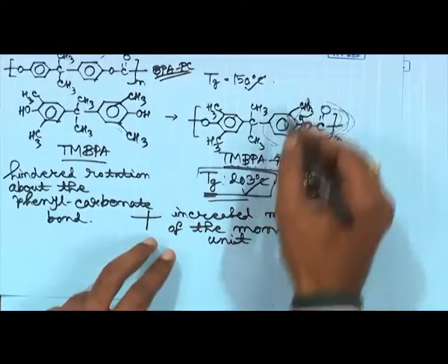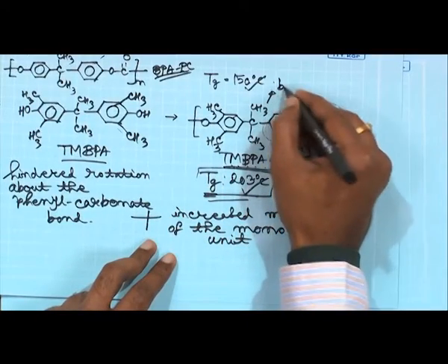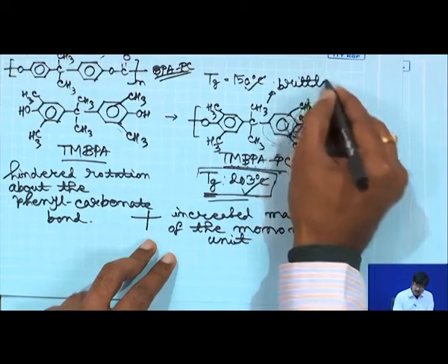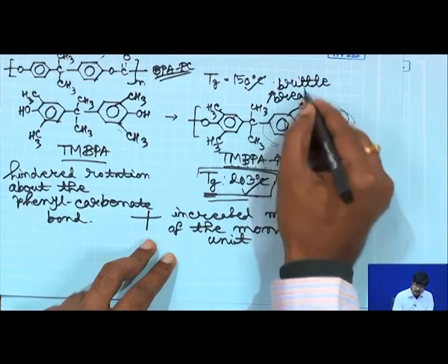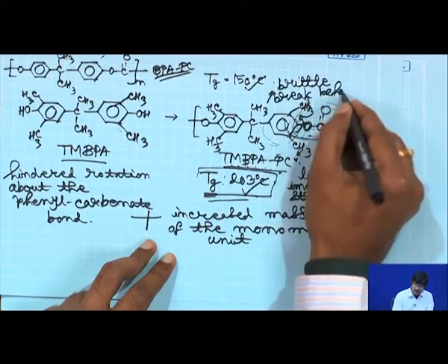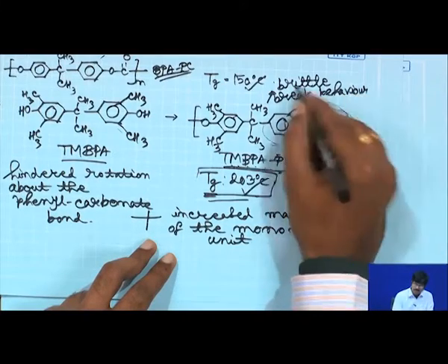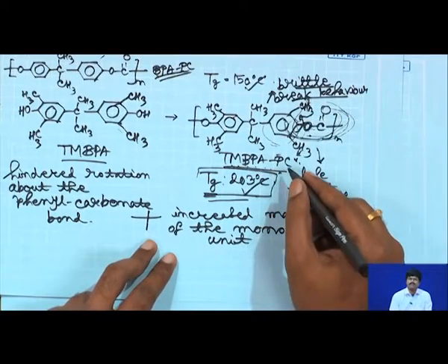Why? We will come to it after, but the fact is that you lost the impact strength. You have higher production cost, agreed higher thermal stability, but you have lost the impact strength. So, what happens is that this material exhibits brittle break behavior. It cannot absorb large amount of energy before it breaks.